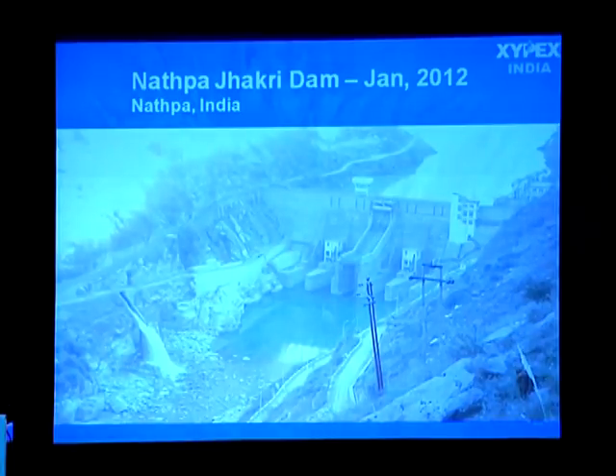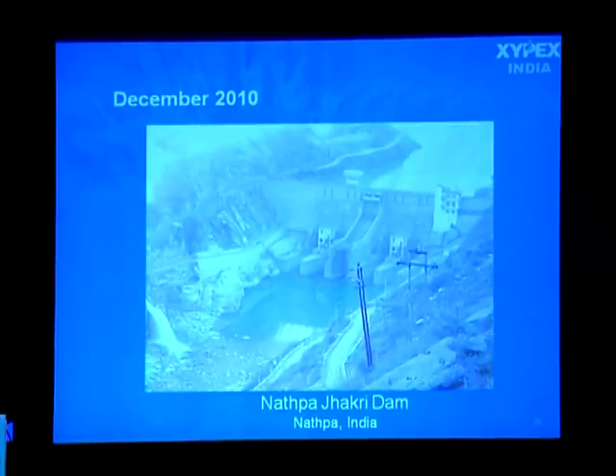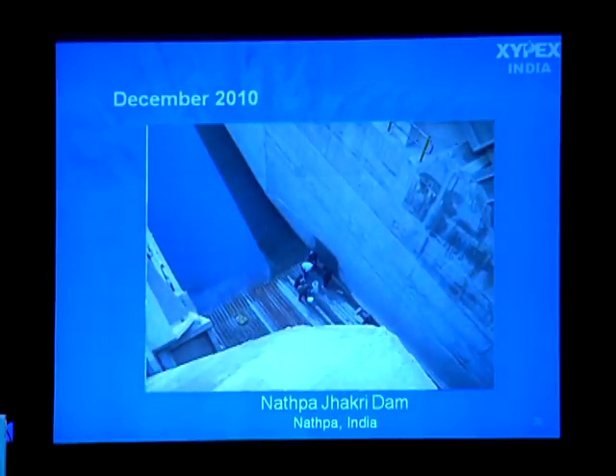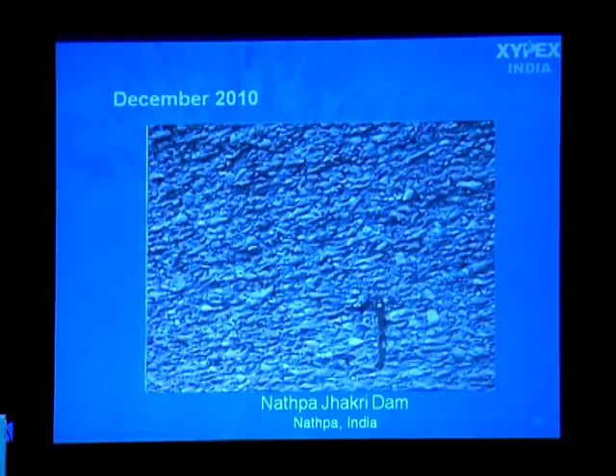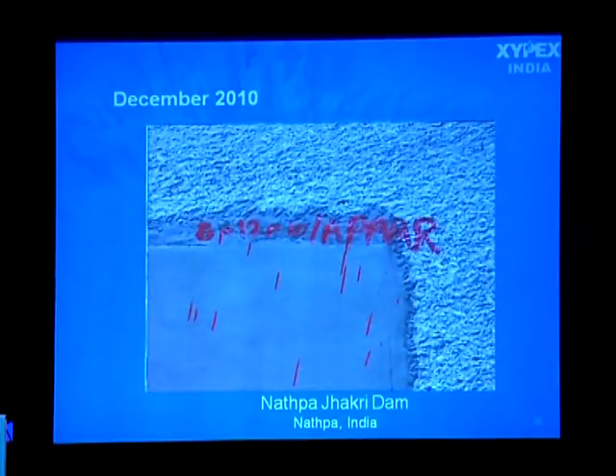So the concern was, how do we actually protect the erosion of this surface? So what we did was, we again did a field trial way back in December 2010. We actually went down right at the bottom of that spillway piers there. You can see the kind of surface erosion there, which was as a result of a high silt content and high velocity water on the spillway piers. We did a small patchwork using our high strength repair material there.